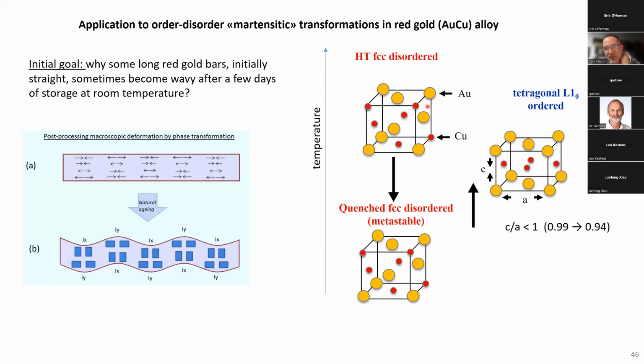We start at high temperature with an FCC disordered phase in which copper and gold atoms sit on FCC lattices, but completely disordered. If we quench it to room temperature, we preserve this metastable FCC disordered phase. But if we leave it a long time at room temperature, or if we heat the material at intermediate temperature, we